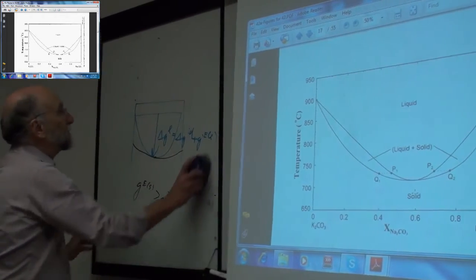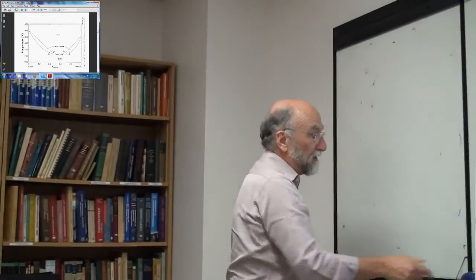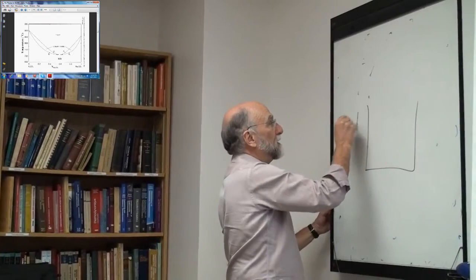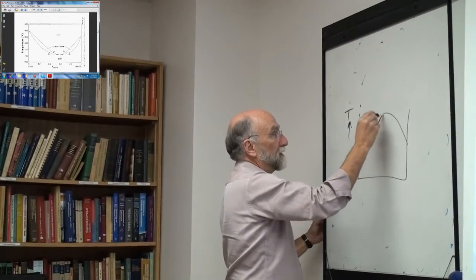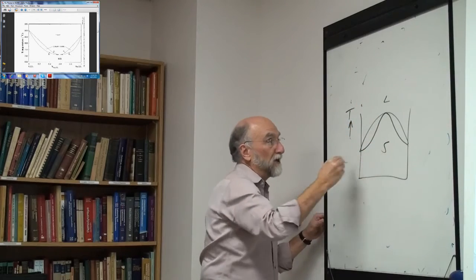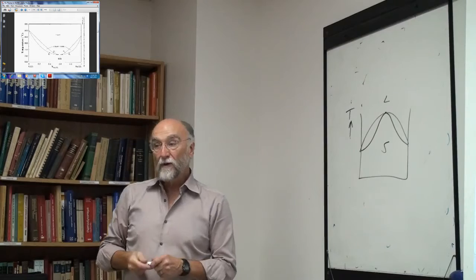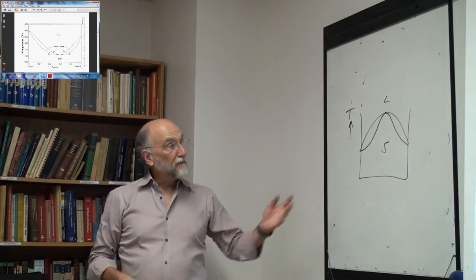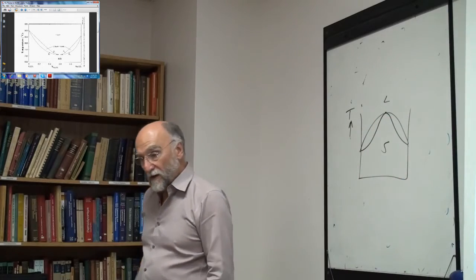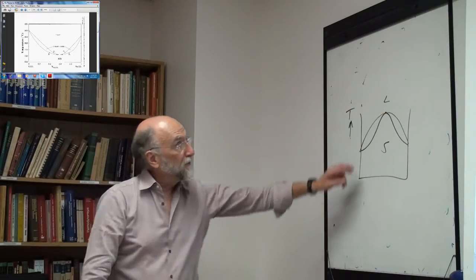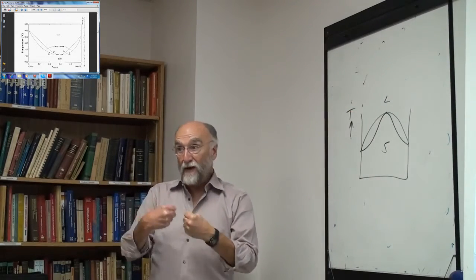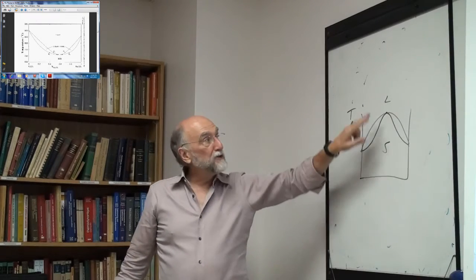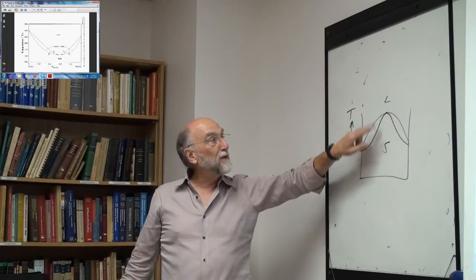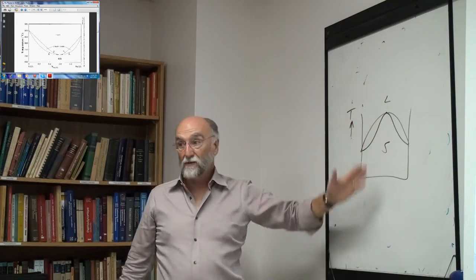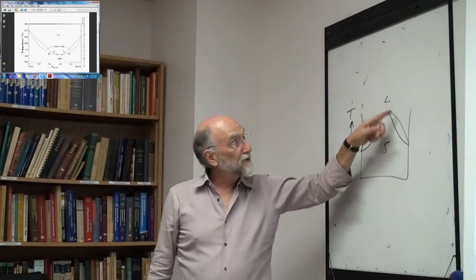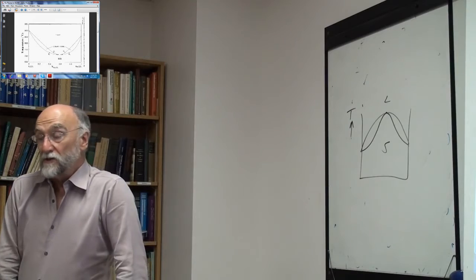In principle, we could have a maximum in a two-phase region of a diagram with complete miscibility. So you could have a phase diagram versus temperature in which you saw a diagram like this. No intermediate phase, complete solid miscibility, complete liquid miscibility with a maximum. Thermodynamically, that's completely possible. All you have to do is the GXS of liquid would be greater than GXS of solid. But this is very unlikely, because if GXS in the liquid was positive, that means the liquid doesn't like to mix, then the solid is going to like to mix even less. That isn't going to be the case if you just have simple regular solution. So I have never actually seen a diagram that looked just like that between a solid and a liquid.